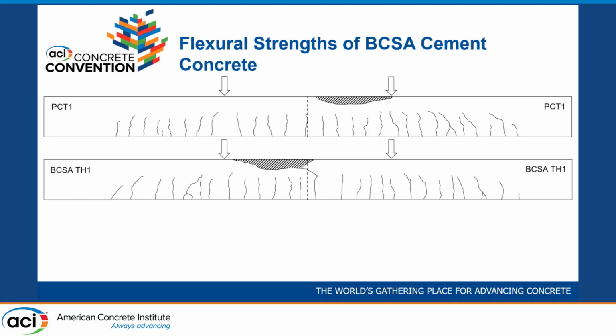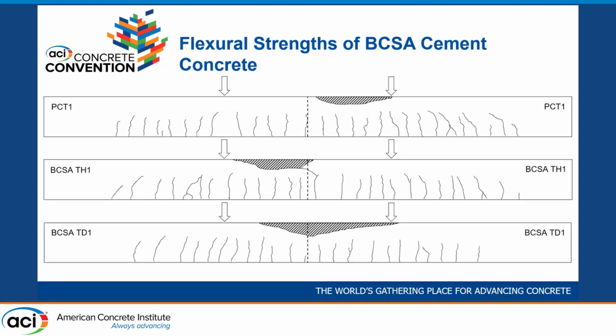For the BCSA beams that we tested at 2 to 5 hours, this is what one of those looked like. And again, lots of distributed cracking. There's compression failure in the middle. The extent of cracking looks quite similar to the Portland cement beams. And the same goes for the BCSA beams that we tested at 1 day of age. The performance of these, just from a qualitative standpoint, looks very similar.